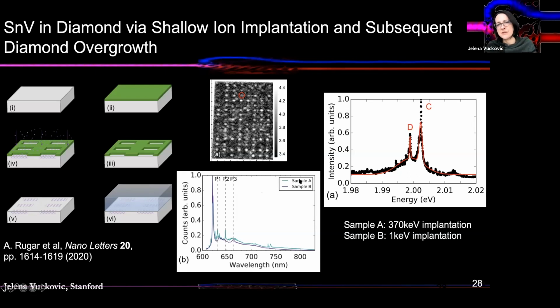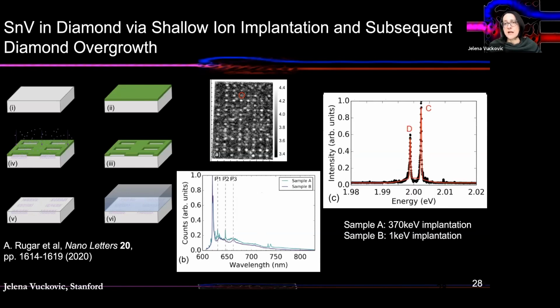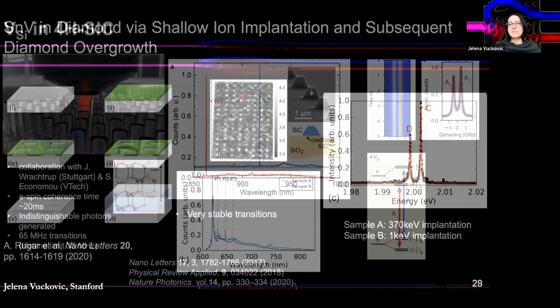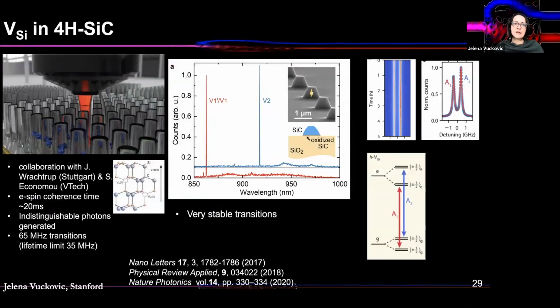And we've shown that with this, we can grow them at desired positions. We have very excellent properties. We eliminate some additional peaks that are a result of damage of the material, and we have much narrower line widths than when we work with high energy implantation. So that's kind of solving one part of the problems, and we're very excited about it.